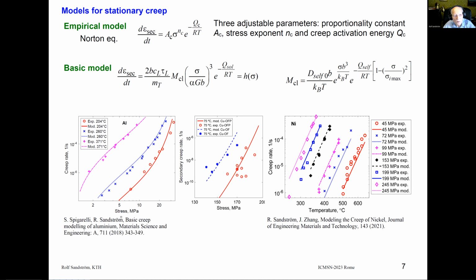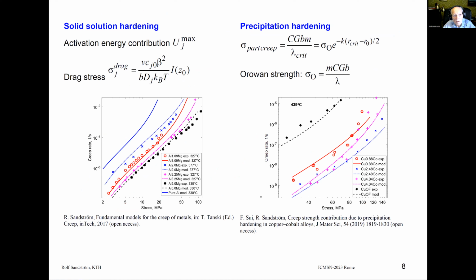And using these expressions, you can describe the creep rate versus stress for pure elements here. Aluminium, oh, this is copper. We have nickel. It's strain creep rate versus temperature. So you can see you can describe these properties quite well. Now, if you move to an alloy, you have to take solid solution hardening and precipitation hardening from particles into account. And this has been, in both cases, quite a classical problem.